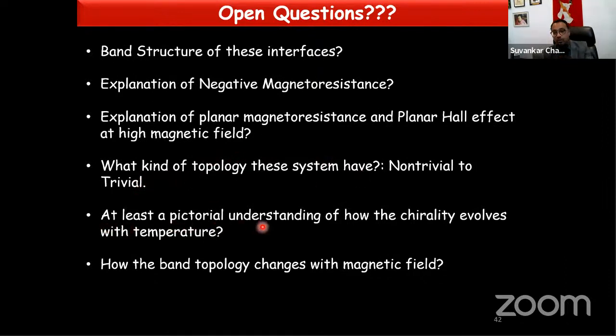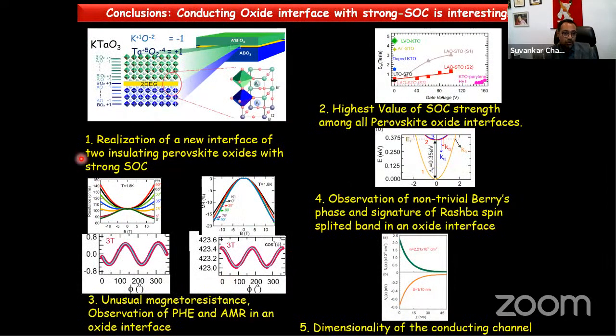And at least a pictorial understanding of how the chirality evolves with temperature and how the band topology changes with magnetic field. So what we have shown is the realization of a new interface with very strong spin orbit coupling, and this is the highest among any oxide perovskite material. Then we show extremely unusual magnetotransport, which can be partially explained by Weyl and partially explained by Rashba physics.